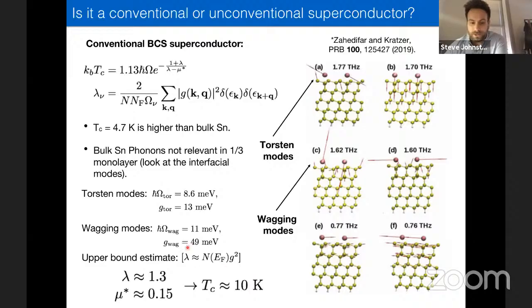You can estimate lambda by just taking g squared and multiplying it by the density of states, essentially assuming that this g value is momentum independent, so it applies over the Brillouin zone. This predicts a lambda of about 1.3, and if you put that into the BCS expressions, you get this annoyingly large Tc of about 10 Kelvin. We can also do Eliashberg calculations, again assuming a momentum independent mode, and we come up with a number not too different from this. And this is for a conventional, standard value of mu star that we assumed.